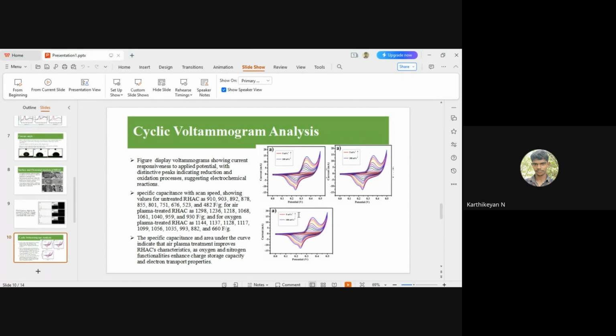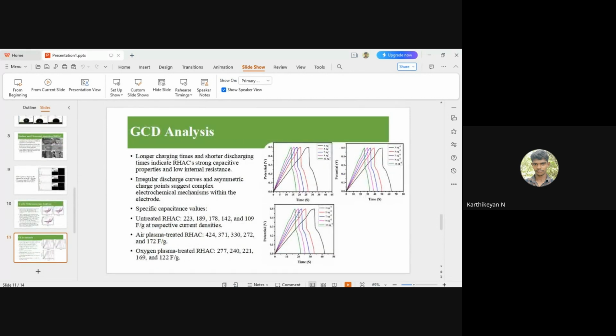The specific capacitance and area under the curve indicate that air plasma treatment improves the RHAC characteristics, as oxygen and nitrogen functionality enhance charge storage capacity and electron transport property. In the GCD analysis, longer charging time and shorter discharging time indicate RHAC's strong capacitive property and low internal resistance. The irregular discharge curve and asymmetric charge point suggest a complex electrochemical mechanism within the electrode.